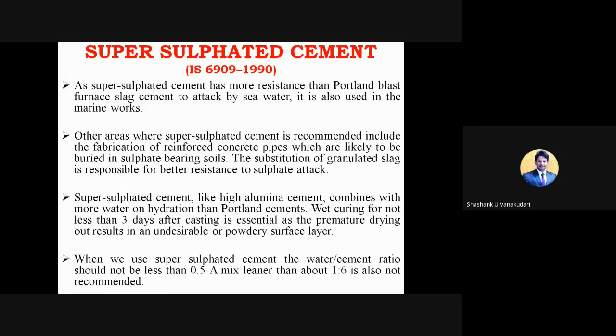This is the same as the previous type, sulfate resisting cement. The substitution of granulated slag is responsible for the better resistance to sulfate attack, and that is the main reason for using this slag-rich cement. Like high alumina cement, supersulfated cement combines with more water during hydration than Portland cement. So wet curing for not less than 3 days after casting is essential, as premature drying results in an undesirable powdery surface layer.